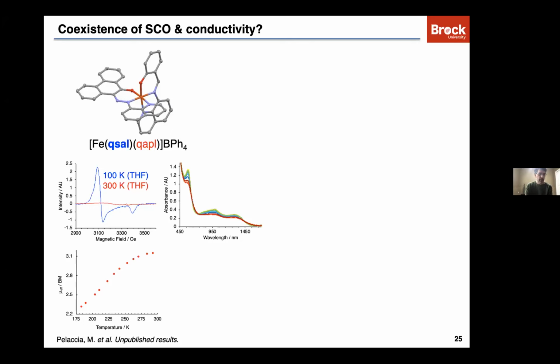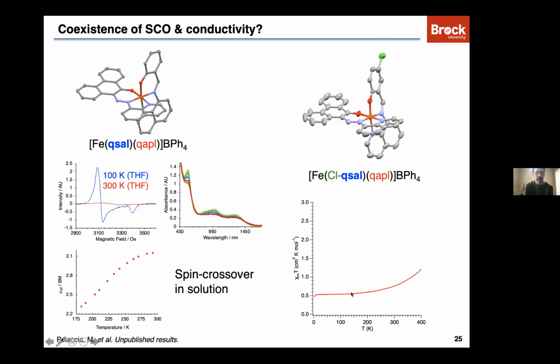Now in these complexes, we can actually generate spin transitions in solution, shown here. This is some EPR data at low and high temperature, UV visible, and some Evans method magnetic studies that have shown the existence of spin crossover in these systems in solution. We do see spin crossover in the solid state, but it's not very spectacular. We see very, very gradual spin state changes between 300 and 400 Kelvin.